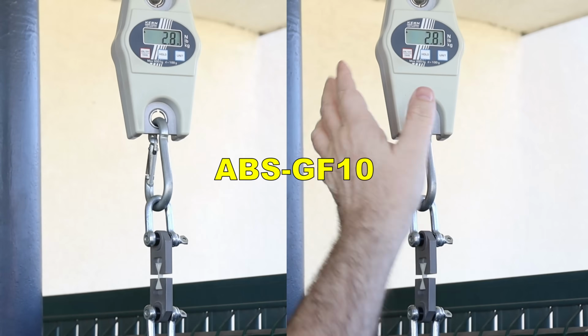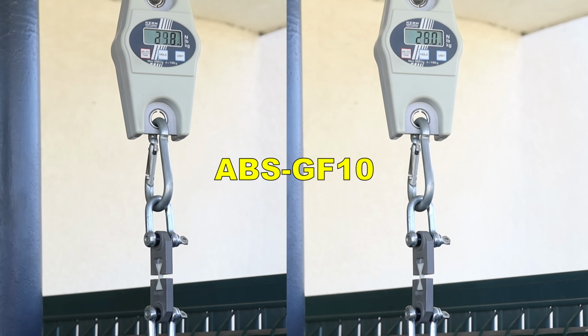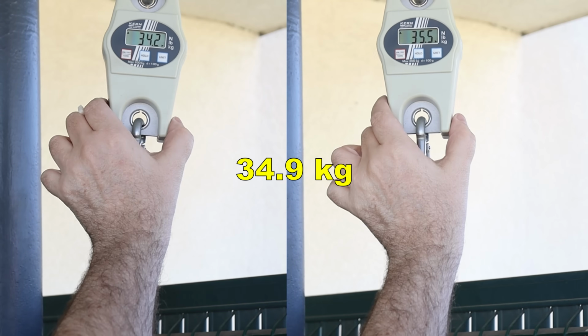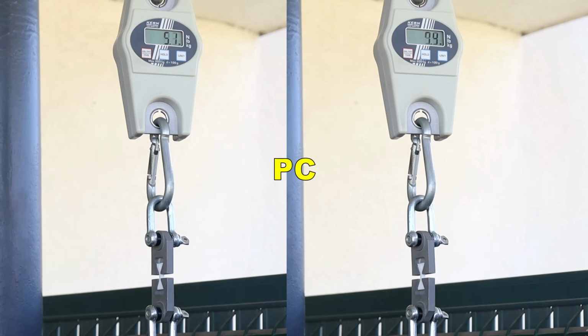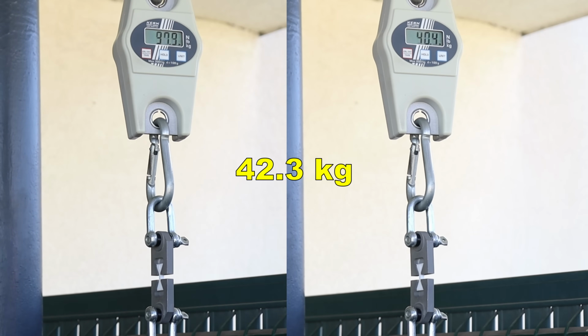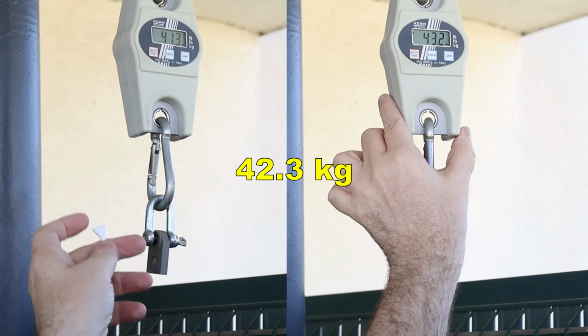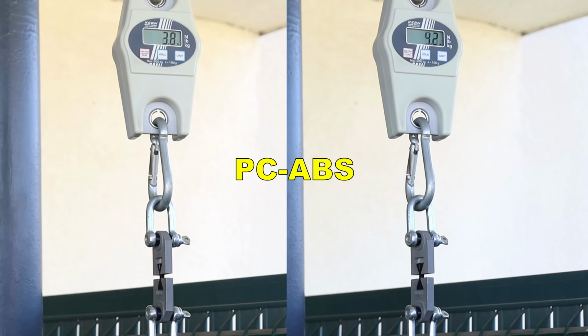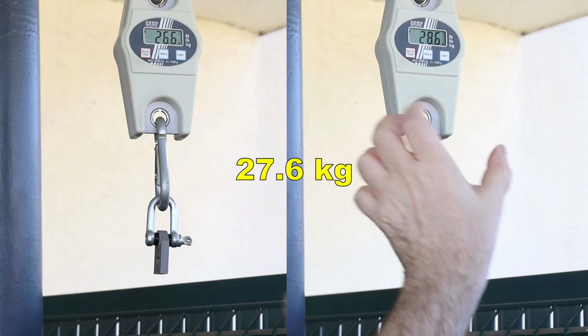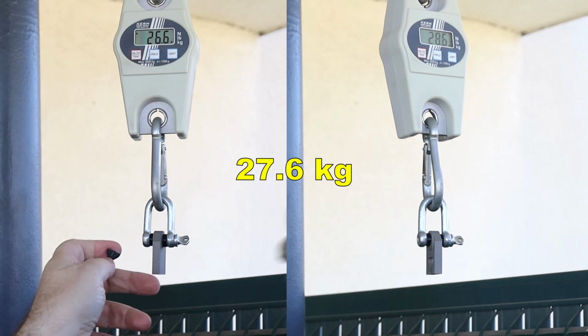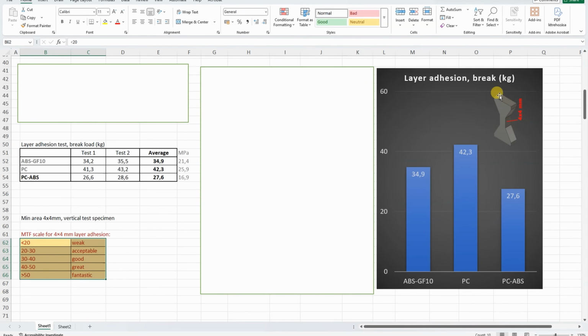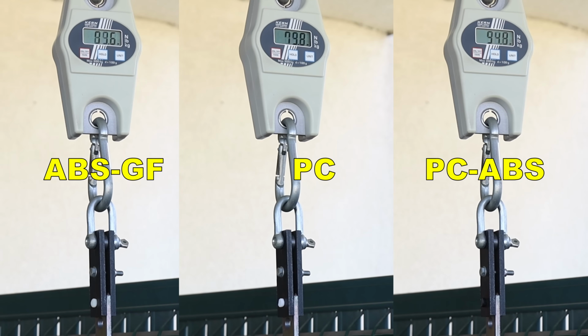Layer adhesion, vertical objects. ABS, polycarbonate, PC ABS. According to my rating for this size of the test object, PC ABS acceptable layer adhesion, ABS-GF good, and polycarbonate great layer adhesion.